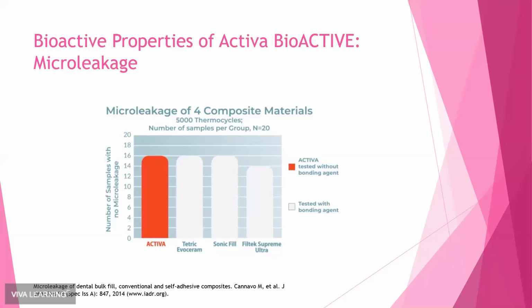But the Activa was actually tested without any bonding agent because the adhesion of the material to the tooth is that good. So you can see that it performed exactly the same as the Tetric and the Sonic materials, and it actually outperformed the Filtek as far as the amount of microleakage that occurred. So it's kind of an interesting way to think about it. We're so used to bonding all the time, but with this material, we're getting just as good of a seal, if not better than some materials, without using a bonding agent.